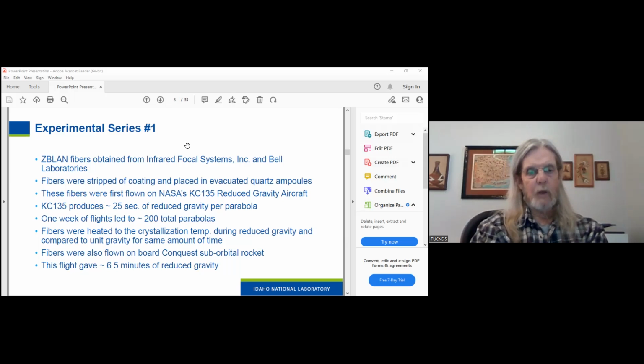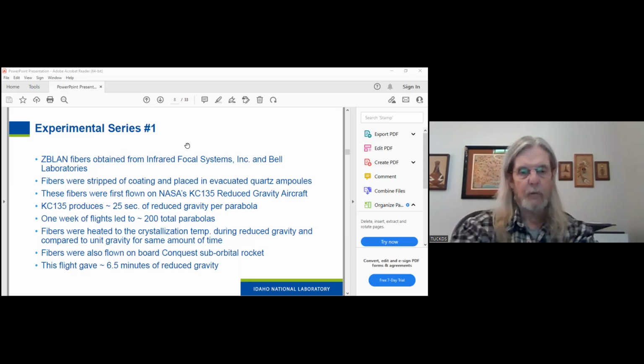So 1 week of flights would lead to approximately 200 total parabolas. And the fibers were heated to the crystallization temperature during reduced gravity. And I compared them to unit gravity for the same amount of time. And after those initial experiments, I also flew on board fibers on the Conquest suborbital rocket. And that flight gave approximately 6.5 minutes of reduced gravity.